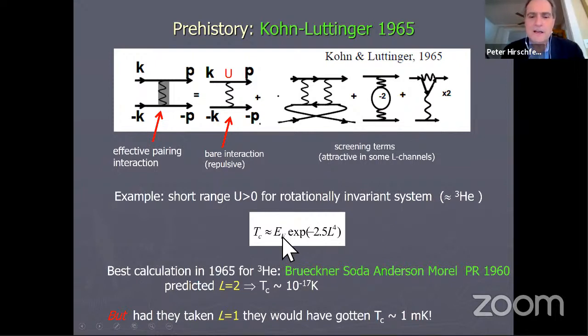And the result that they got, this is kind of fascinating, was very similar to the BCS result, except it had a factor of e to the minus 2.5 L, L being the relative orbital angular momentum of the Cooper pair, to the fourth power. And the prefactor is the Fermi energy instead of the Debye frequency, as in ordinary superconductivity. Now, L, the best calculation that was available at the time for superfluid helium-3, which was the fermionic system that was most exciting from the point of view of pairing or superfluidity back then, the best calculations gave an angular momentum of 2. And so Kohn and Luttinger predicted that Tc would be 10 to the minus 17 Kelvin.